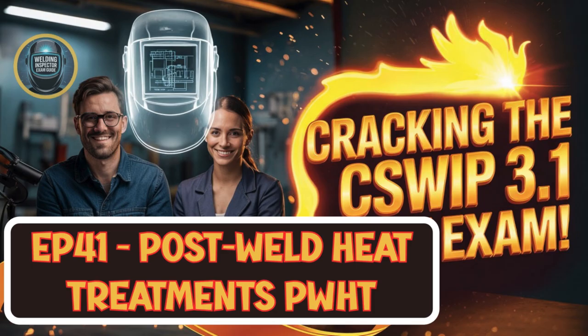Just like you need to control the heating, you need to control the cooling afterwards, and for exactly the same reason. Cool down too fast, and again, you risk creating those damaging thermal gradients, leading to distortion or even cracking as different parts shrink at different rates. So slow cooling too, down to what temperature? Usually the codes specify controlled cooling down to about 300 degrees Celsius or 575 F. Again, below that temperature, the steel has regained enough strength and toughness that it's much less susceptible to damage from temperature differences. So often, once it's below that 300 C mark, you just take it out of the furnace or turn off the local heaters and let it cool naturally in the air.